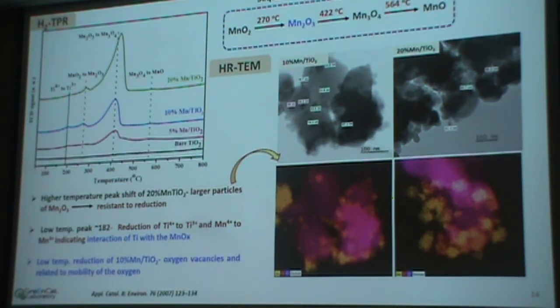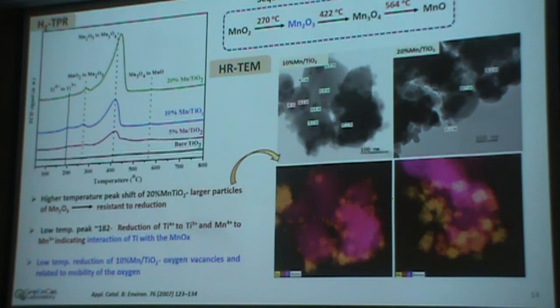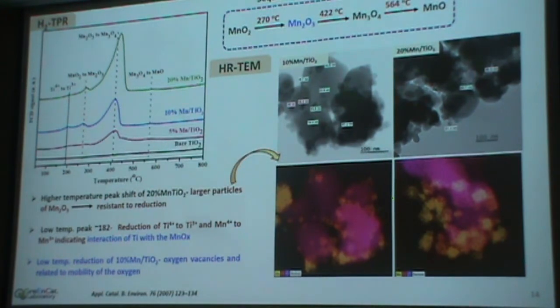And increasing particle size was also clearly observed from the TEM analysis, where in 10% Mn you will observe small, well dispersed particles, whereas the extent of aggregation is increased in 20% Mn. As for the structure of the particles, it is cubic in 10% Mn, whereas in 20% Mn hexagonal phases are observed. And cubic phases generally have normal edges that create defect sites and enhance the mobility of oxygen.